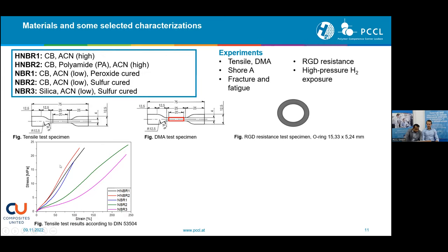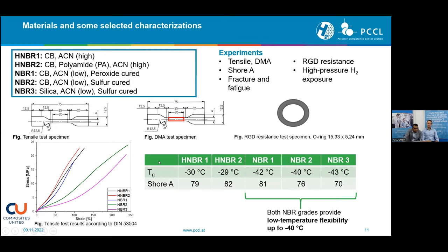If I briefly explain, the two HNBR grades are showing stiffer material behavior, together with NBR1, which is peroxide cured, and the sulfur cured ones show a bit softer behavior compared to the other three, and the silica filled one even softer and more toughening behavior. So further, in terms of Shore hardness, which is very important for RGD, especially considering the gas intake, they are all in the good range, around 80 Shore A.